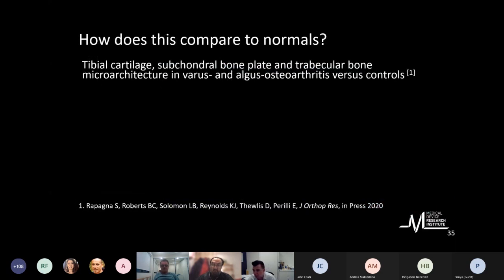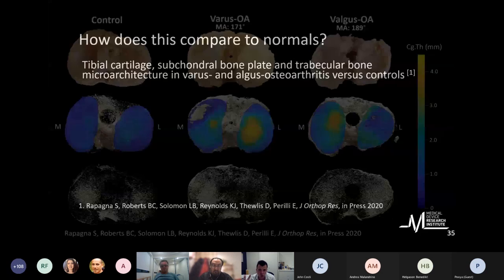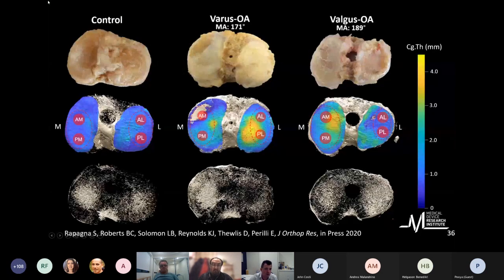How does this compare to normals? That's another question that we got, because we were just looking at osteoarthritic patients. So we have looked at tibial cartilage, subchondral bone plate, and trabecular bone microarchitecture in varus and valgus osteoarthritis patients versus so-called controls, non-OA. And these are photographs on the top, micro-CT images with the cartilage distribution in the middle, and then the bone underneath, the subchondral trabecular bone. And you see that in the controls on the left, in blue, there's a 1 millimeter thick cartilage all over the medial and lateral plateau, whereas in varus aligned, we have less thick cartilage medially, shown by darker blue, and brighter colors laterally, which means thicker cartilage, and the opposite is seen in valgus.